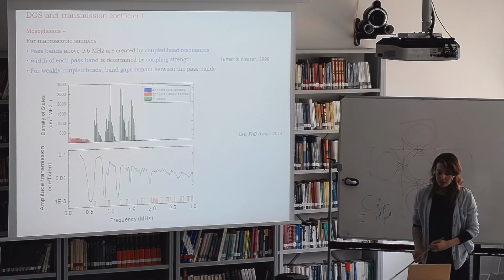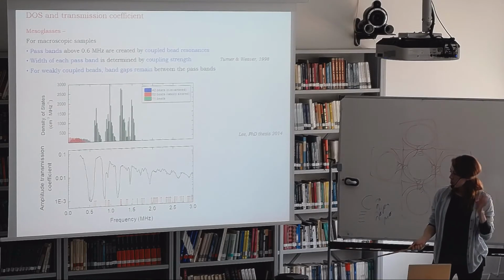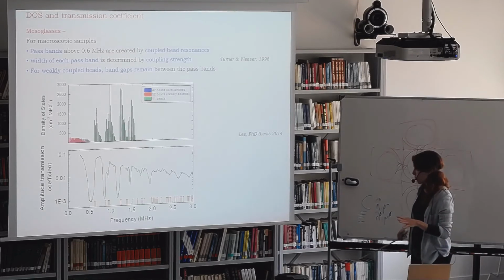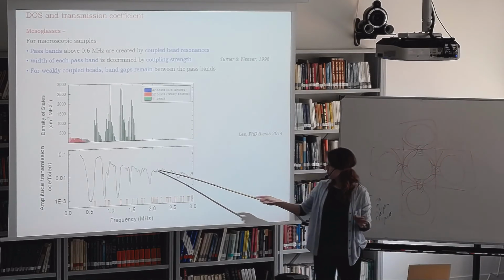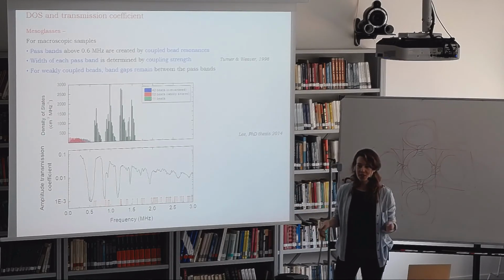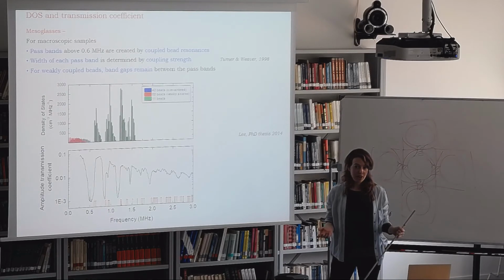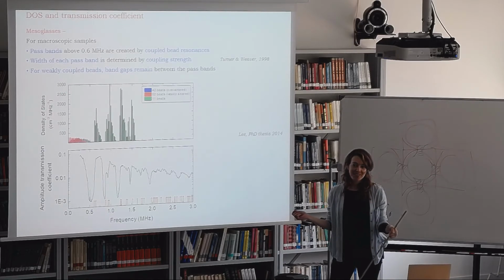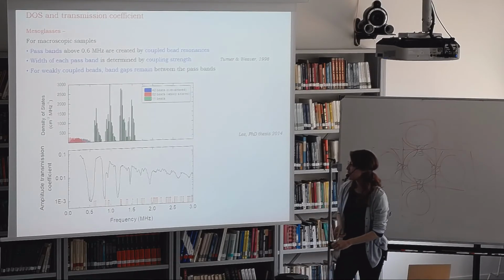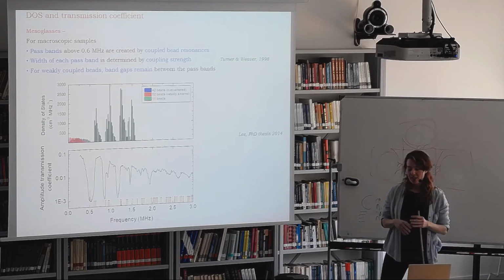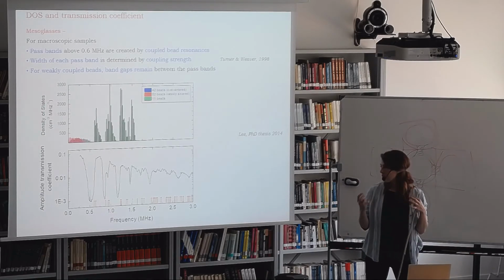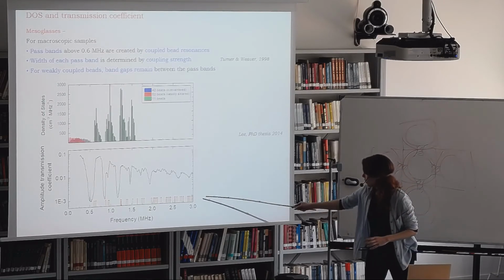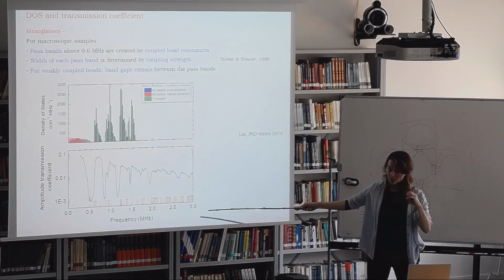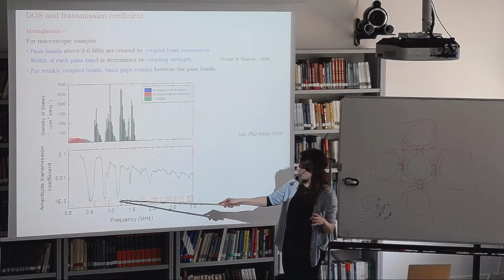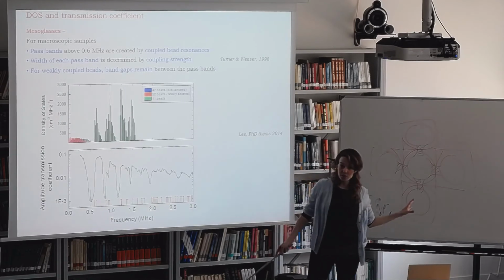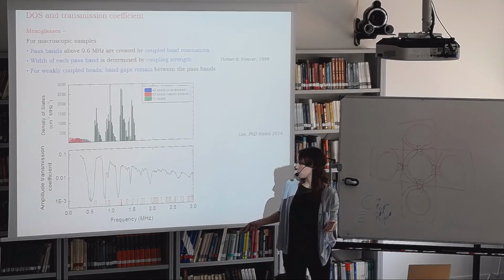So, if we look at the average transmission as a function of frequency for these samples, then we actually see regions of high transmission and then also band gaps. So actually, interesting question. Why would we have band gaps if the samples are completely random? It's because of the way sound propagates through the samples. It doesn't propagate as if through a solid, but it's really coupled resonances of the individual beads. So actually here we're plotting resonances of the individual aluminum beads. And so if you have an area where you start to have a lot of resonances, they sort of couple together and you have transmission. But in other areas, you just don't have transmission there.